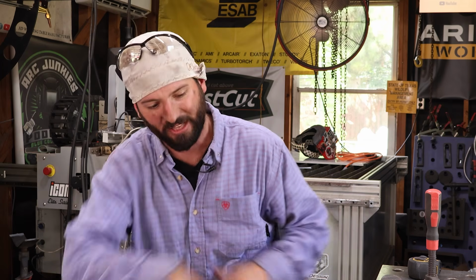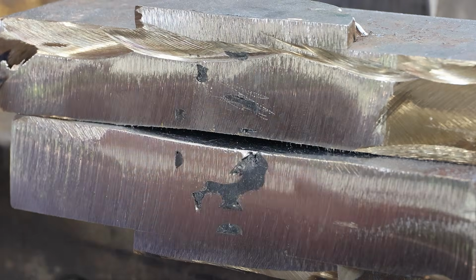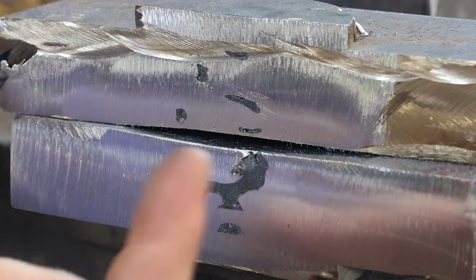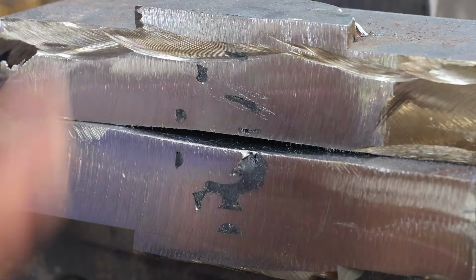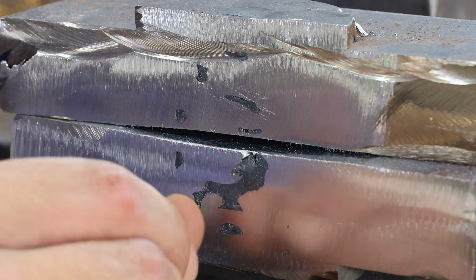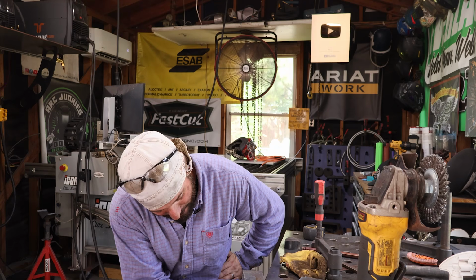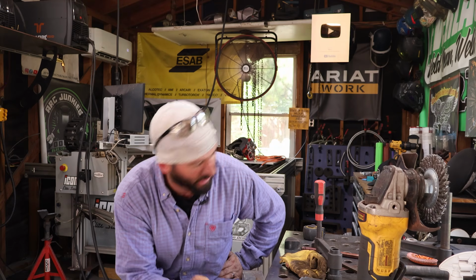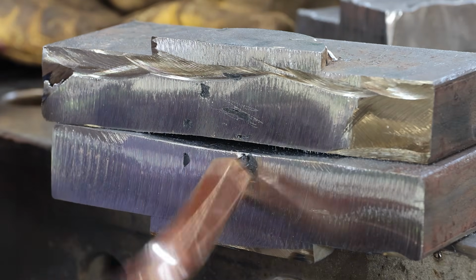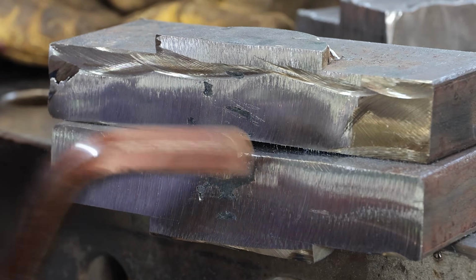I would say we probably were in the range of too cold of voltage and too low of amperage in order to make this continuous weld. But if you were to take it in stages, you would not see this. This is the definition of trapped slag. That is just crazy how much slag is in there. Trapped slag is a big issue, even though it looks kind of solid and it's not really coming out of there too much. It's kind of chipping out.